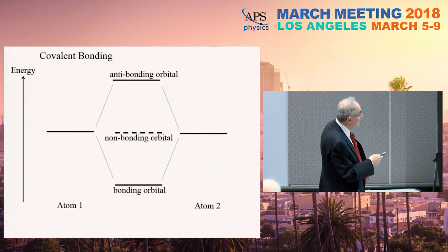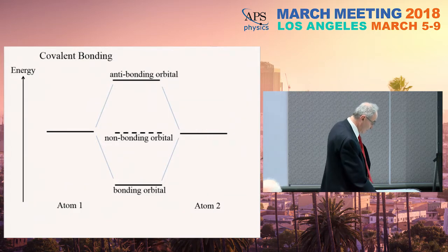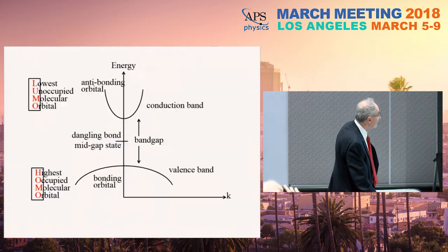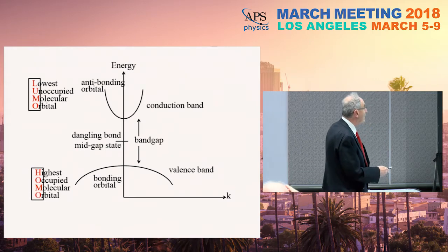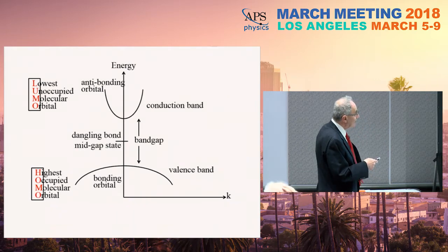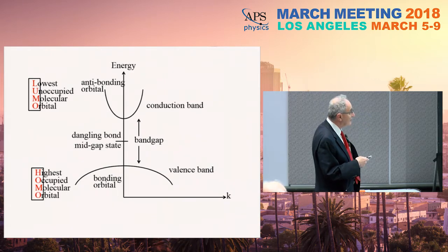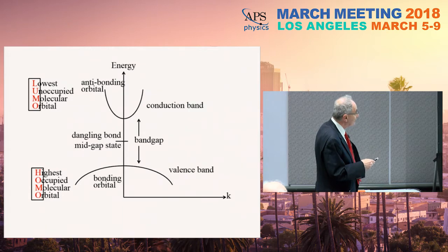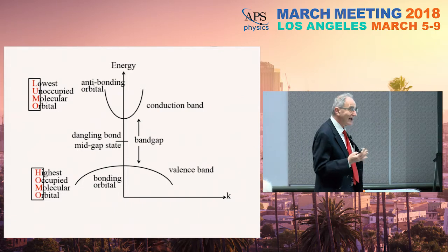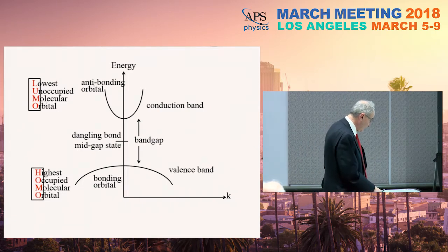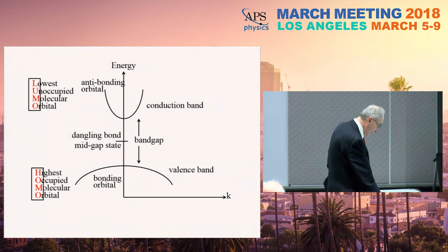The difference between the antibonding and the bonding we can think of as like a semiconductor bandgap. If all we have left are the non-bonding orbitals, this leaves energy levels right in mid-gap. These mid-gap levels are the biggest problem in semiconductors because they can capture an electron, then a hole, then an electron and a hole — acting as a catalyst for electron-hole recombination, which is extremely destructive to semiconductor function.